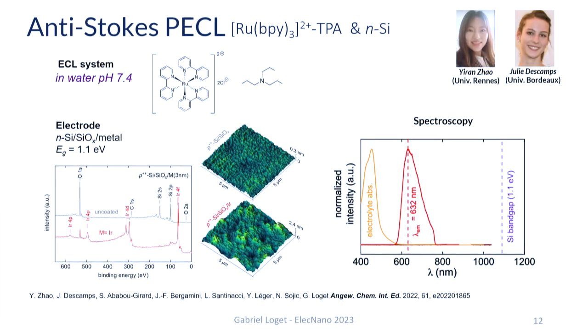The problem with silicon is that it is highly unstable in aqueous electrolyte, especially when we use it as an anode. So we needed to find a way to protect it, and for that we coated it with a tunnel silicon oxide layer and different metal coatings. We tested different ones. Here you can see the characterization data for iridium. In the AFM, the gray data are before deposition of the iridium thin film, and the red data are after the deposition of the iridium thin film.